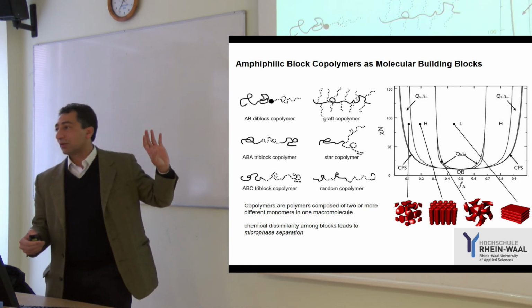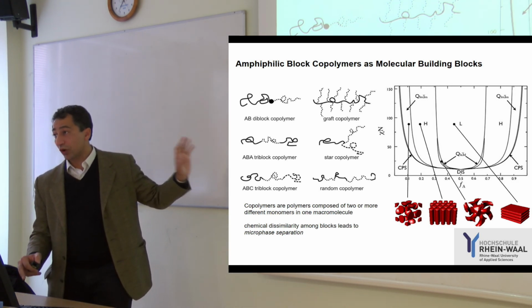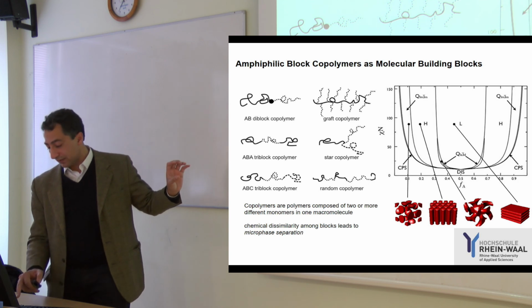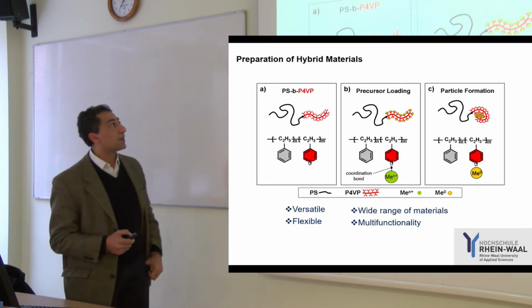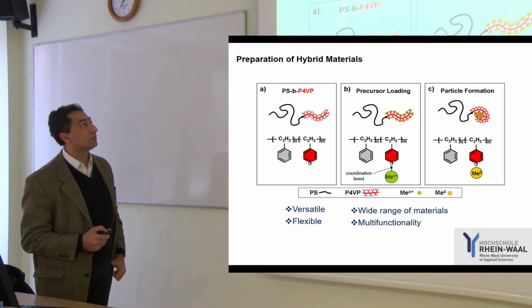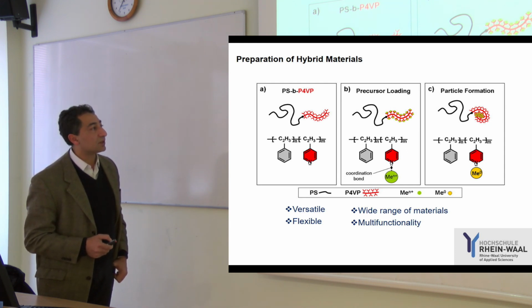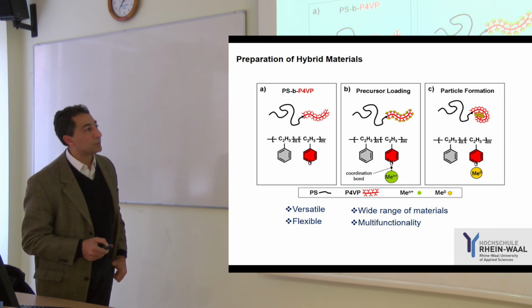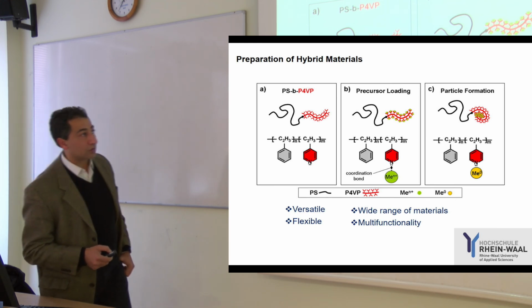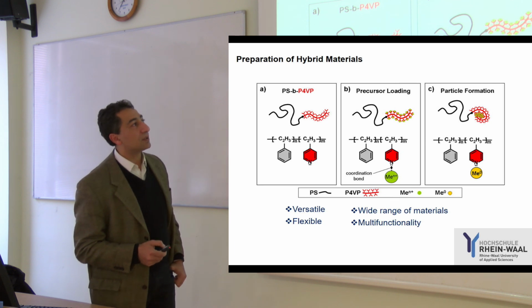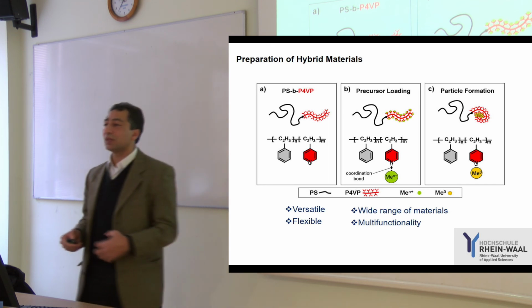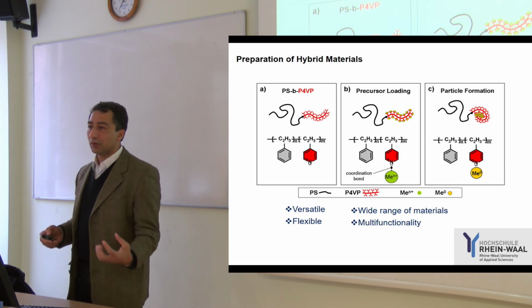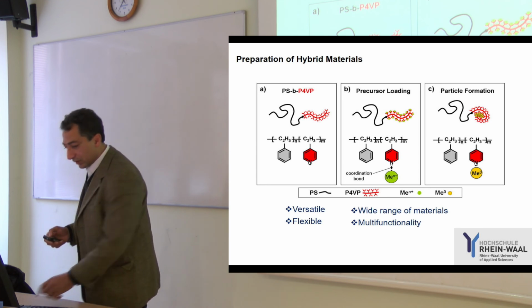Right now we are speaking about polymer. However, we are looking for inorganic filler inside the polymeric matrix. We make a very interesting model for it, polystyrene-polyvinyl pyridine, and we use the chemistry. There is a very nice link between these groups and inorganic precursors, so we can use this self-assembly process to align the inorganic in a well-defined structure by using the self-assembly of the block copolymer. This is the whole story about it.